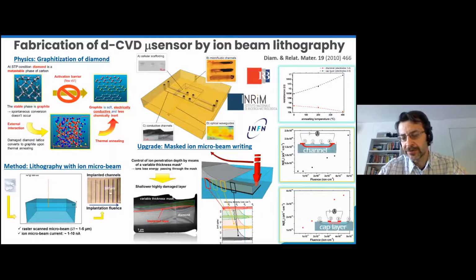First of all, by doing this, we introduce defects. If we introduce a high concentration of these defects, then the lattice of the diamond is completely destroyed. If the concentration is below the threshold for amorphization of diamond, upon annealing, the crystal lattice can be recovered. In the regions where the concentration of defects is so high that the material cannot recover upon annealing, the material transitions into the graphite state.